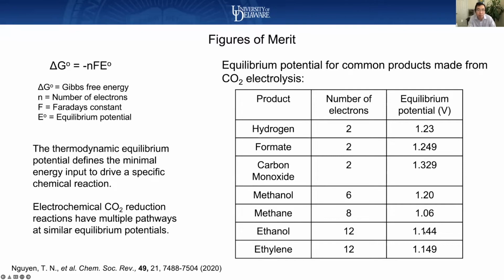drive certain reactions. The challenge for CO2 reduction, particularly in aqueous environment, is that multiple reaction pathways can occur at similar equilibrium potential. This table on the right summarizes the major products you can make from CO2 reduction. Formic acid and carbon monoxide are two-electron reduction products, and then methanol, methane, ethanol, ethylene. Ethylene is one of the very popular multi-carbon products, and it involves 12 electrons. If you look at the thermodynamic potentials, they are very similar to each other, plus or minus 0.2 volt. And if you consider the overpotential you have to apply to the system, at a practical, realistic applied potential you can drive all the reactions at the same time. So selectivity becomes one major challenge. That's why we need a catalyst which can selectively promote one reaction pathway and suppress others.